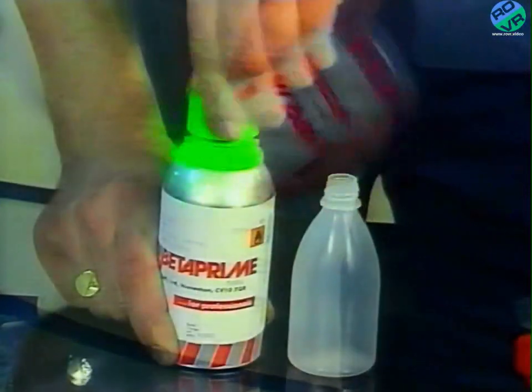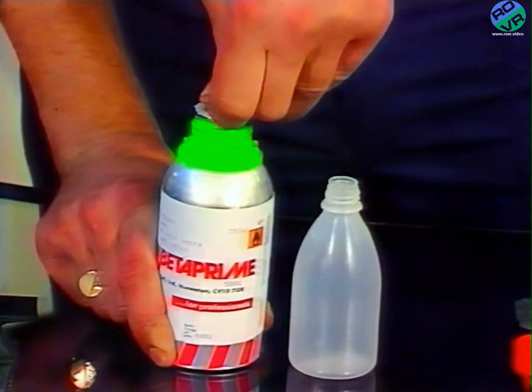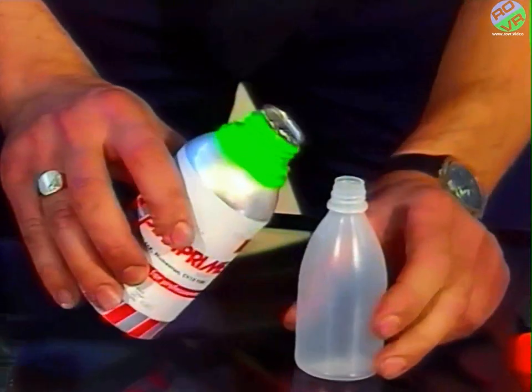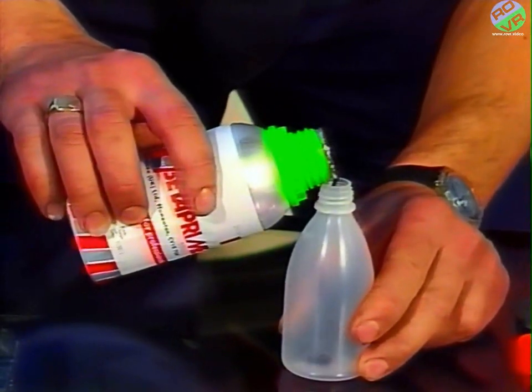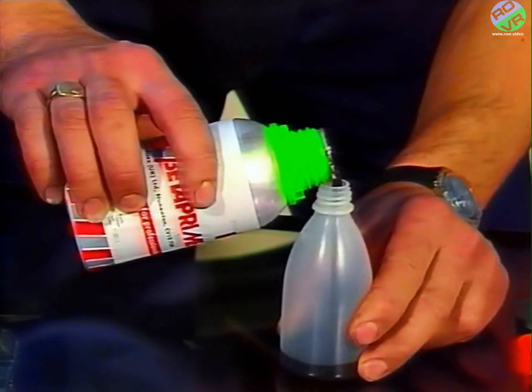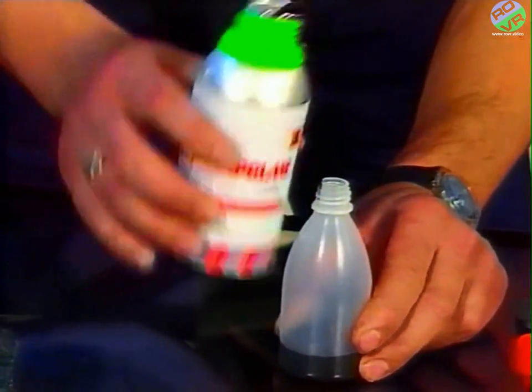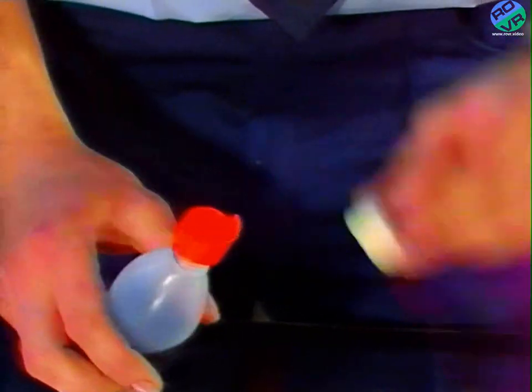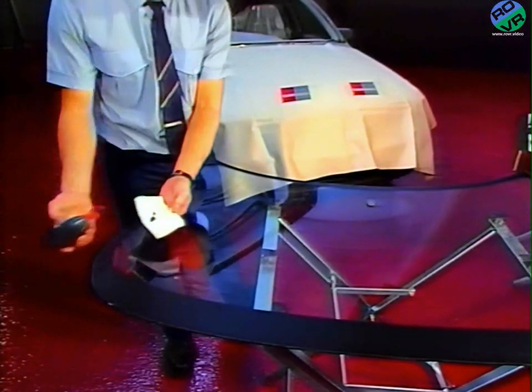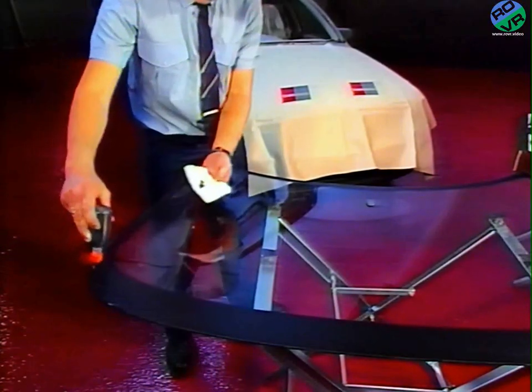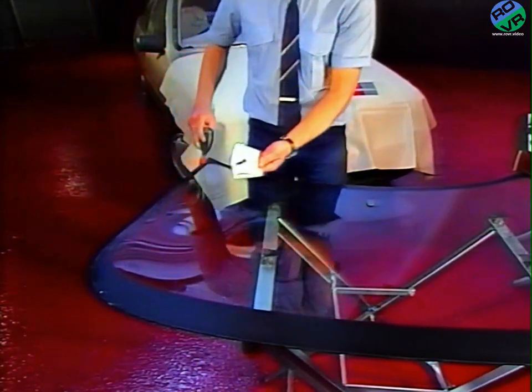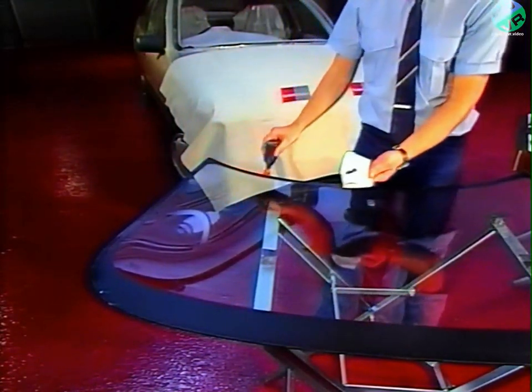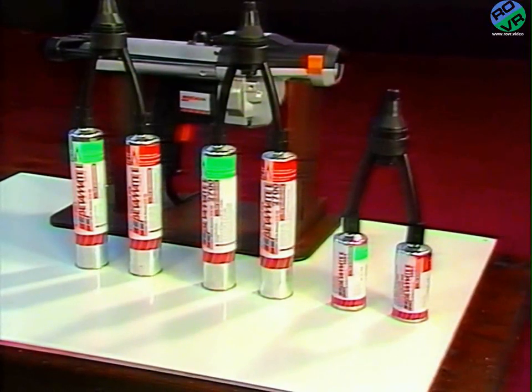Take the Betaprime 5001 and shake it for at least a minute. Remember, without this black primer, ultraviolet rays will attack the adhesive and in time can lead to a failed installation. Apply it using the Gurit Essex applicator bottle and felt, or a wire felt, in a continuous flowing movement to give an even film. When the primers have dried, you're ready to use the Beta gun.